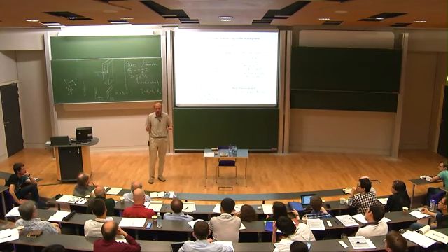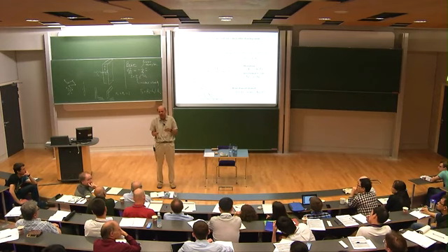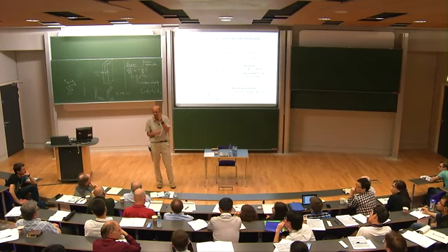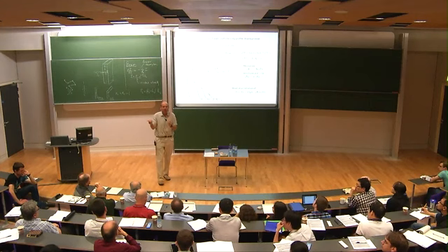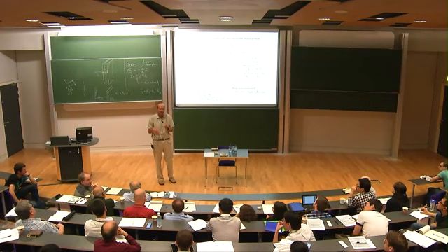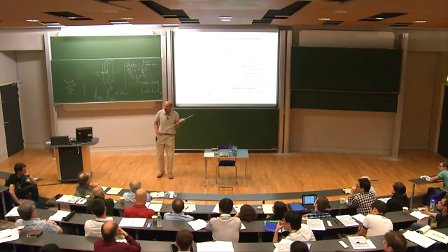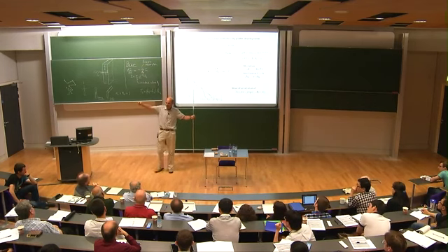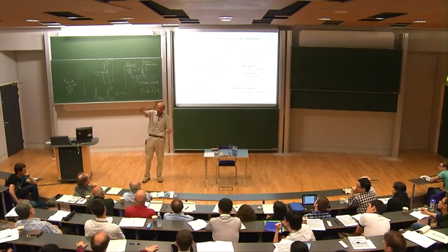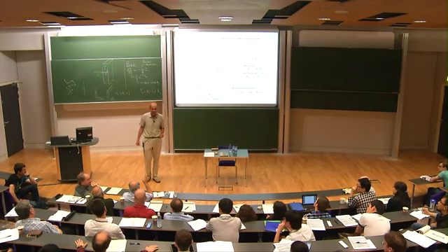And that's known to be about 4 parts in 1,000 or something like that. So there is a tiny effect, but it's very small. But you're not even going to the isotropic state. You're just going between 2 slightly different nematics. Well, yeah, the remark was I'm not even going to the isotropic state, but I would like to go to the isotropic state because I get the full stroke of this. This Terentjev experiment was going to the isotropic state. He gets 300%. So yes.